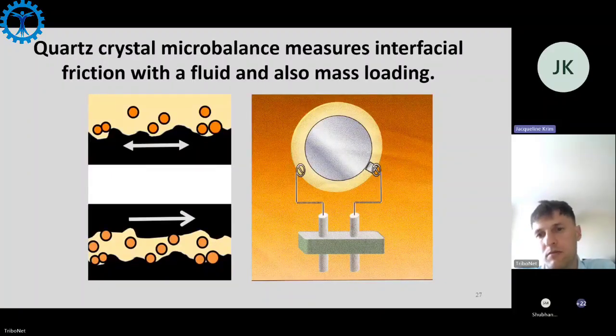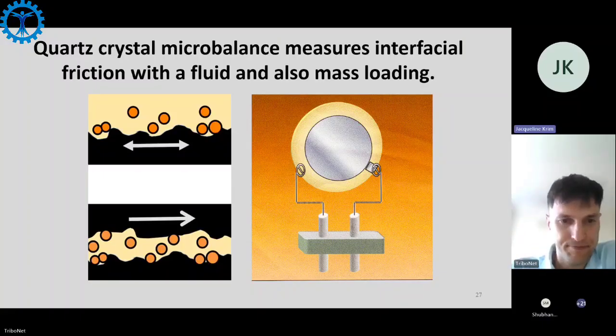QCM, it's about this 1 centimeter across. And on the top left, we see it vibrates horizontally in the fluid with the nanoparticles. And it really is very similar in speed, loading forces, etc., to a contact that I show below of two surfaces in the hydrodynamic regime. It's taking measurements of what is the slippage along one of those interfaces.